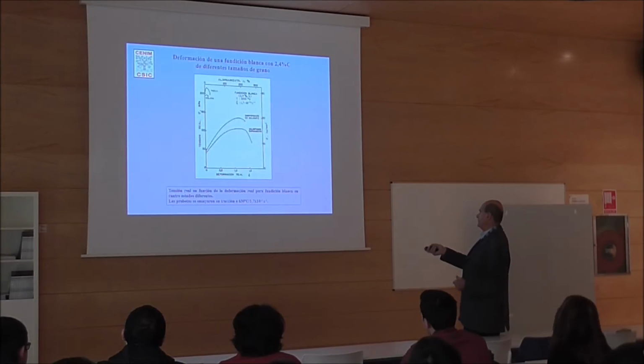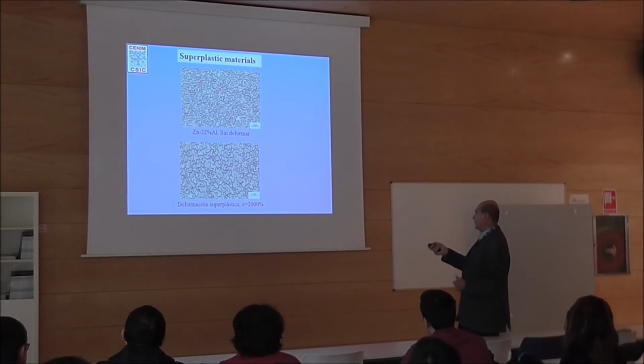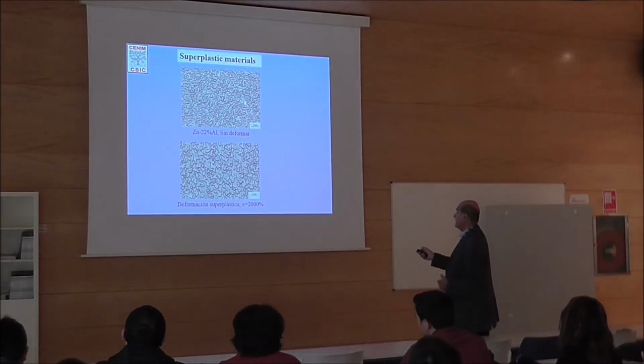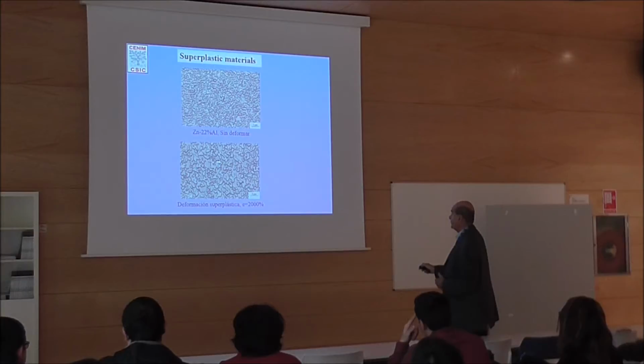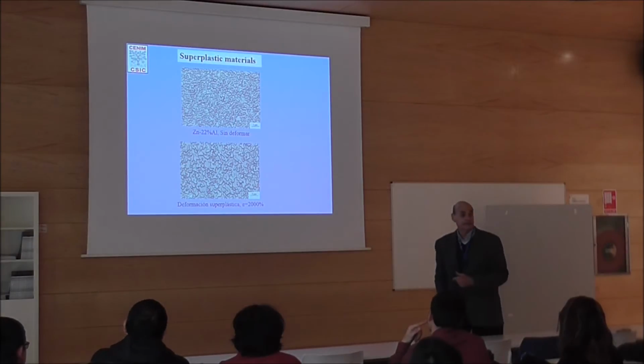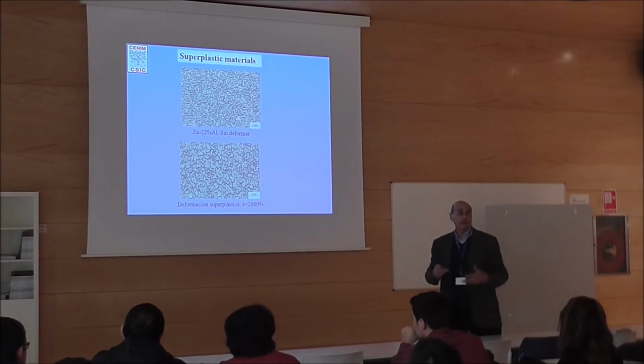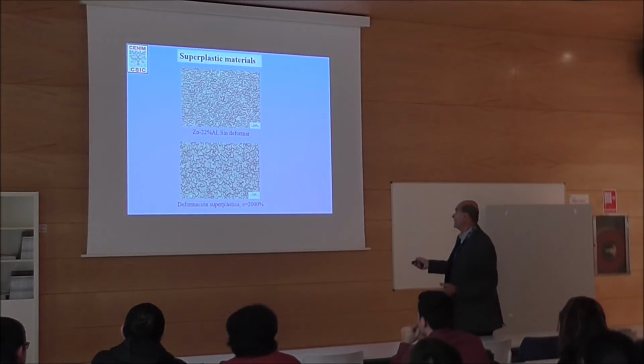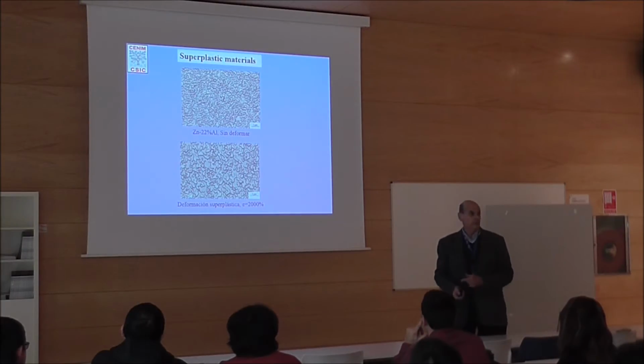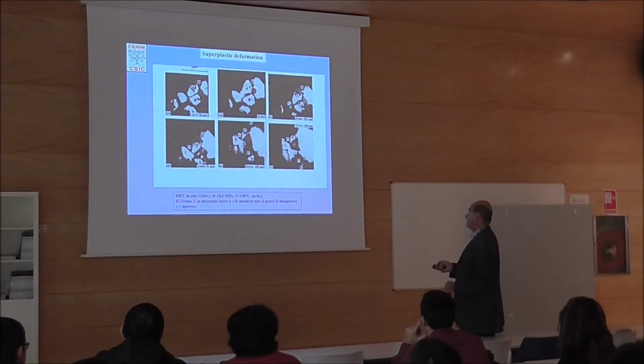And this is okay. This is the material. This is an example of equiaxial grains. We have equiaxial grains at the beginning of the sample, and after 2000% deformation, equiaxial grains are still existing. So no grain elongation, no slip, because no slip creep. But a little bit of grain growth, but equiaxial grains.